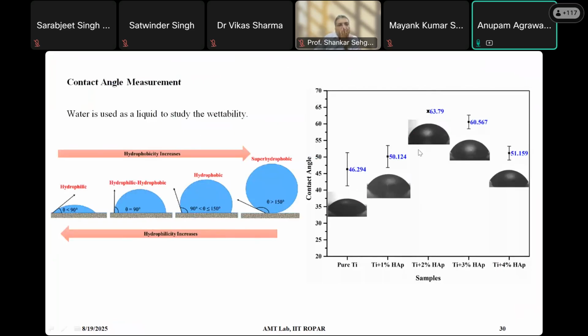In one way it is okay for us. We were fine that the titanium is non-toxic and is not doing anything to the bodily fluid or anything. Even if some bodily fluids are coming into the pores and reacting with hydroxyapatite, they may actually increase the bioactivity. So even though it is hydrophilic, it's fine, we were okay with that.